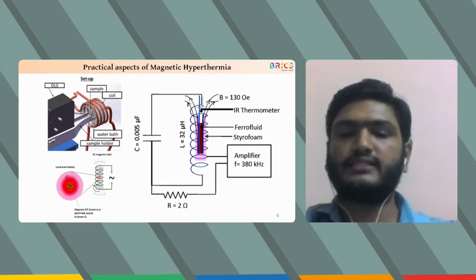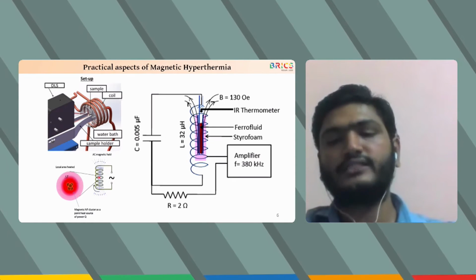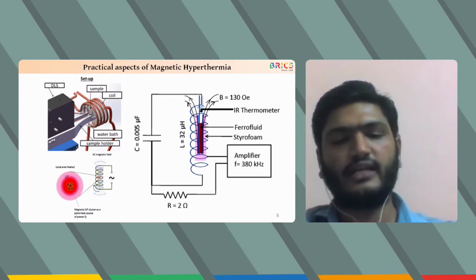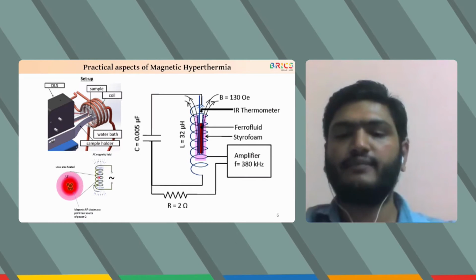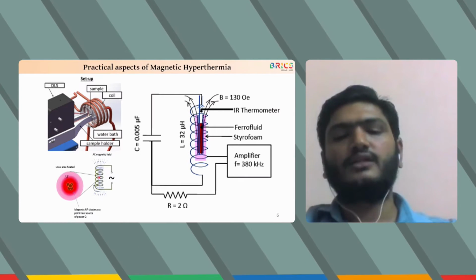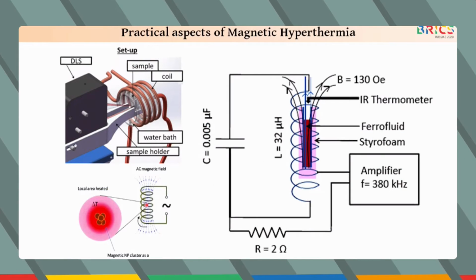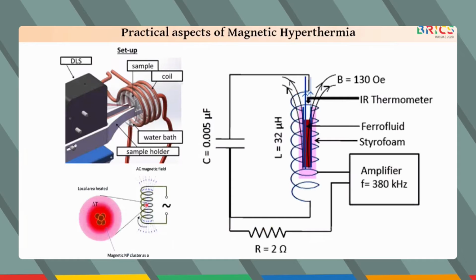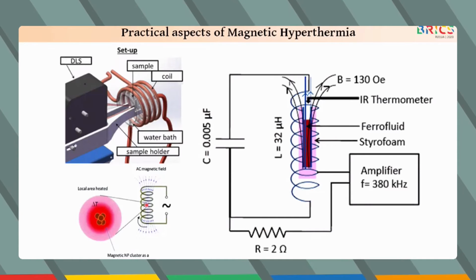This particular system provides a field of just over 0.01 Tesla at a frequency of almost 400 kilohertz with a current of 30 ampere flowing in a wire. So the high currents required for producing high magnetic fields led to substantial resistive losses in the coil and therefore significant radiative heating. So what do we actually measure?